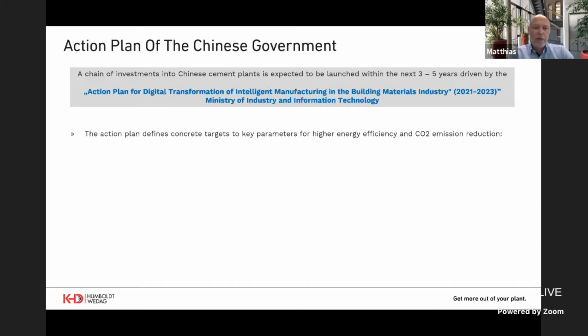So this action plan defines very concrete targets for energy efficiency and CO2 emission reduction. For example, the program sees that the heat consumption for clinker production should be reduced down to 670 kilocalories per kilogram clinker, while the current national average is about 780. So that is very ambitious, and the Chinese are very serious about this.